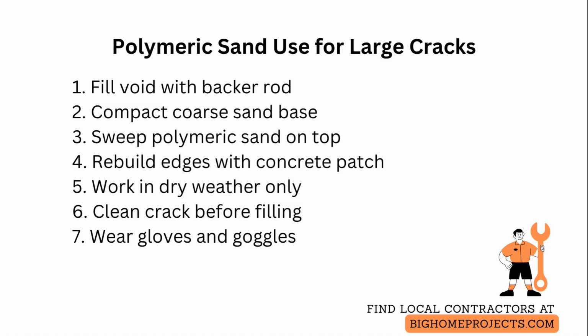Work in dry weather and follow full cure times. Do not apply polymeric sand if rain is expected within 24 hours, because premature moisture prevents proper polymerization. For best adhesion and longevity, clean the crack of dust, roots, and loose material with a wire brush and compressed air or a shop vacuum before filling.